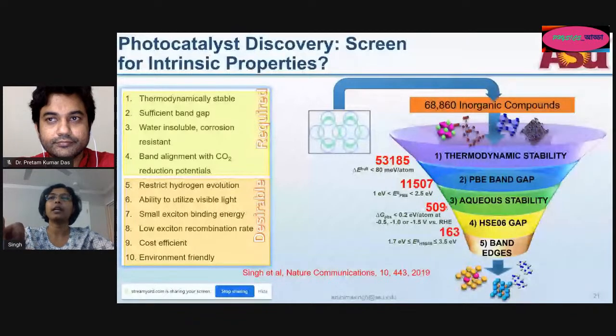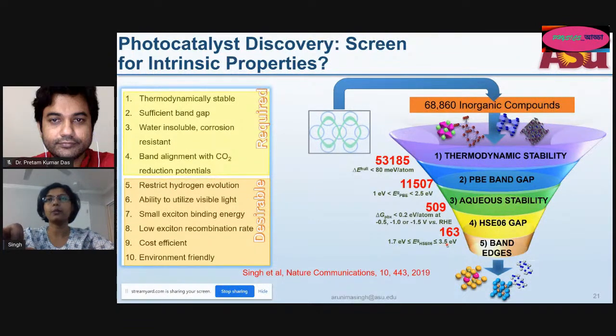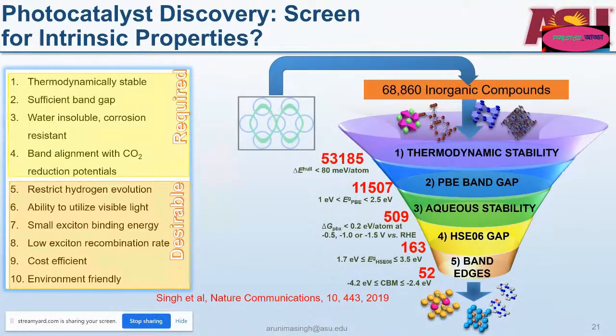And then we did more accurate calculations of the band gap, and we found about 163 were in the range of visible light spectrum. And we also chose a slightly higher value than the 3 eV range, which is in the visible light spectrum, to account for the changes in band gaps due to surface states or perhaps defects in the system, which we haven't really exclusively considered in this work. And then we looked at the band edges. It should be enough for the CO2 reduction potentials. And we found there are 52 materials which emerged out of this screening. So from 70,000 materials, we were able to get to 52 materials which had these properties which are absolutely required to be a good CO2 photocatalyst.